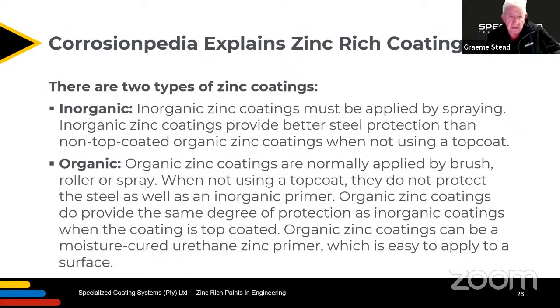Now, I must emphasize that the spraying process must include agitation of the pressure pot or container where the zinc is being sprayed from, whether catalyzed or single pack, because the zinc will tend to settle, and one must have the correct amount of zinc in the spray line at any one time.